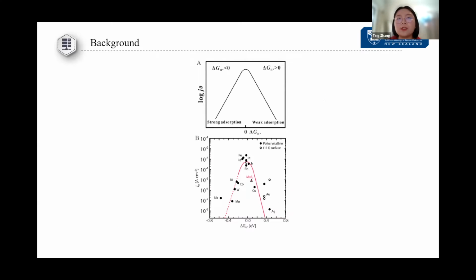According to the HER research, the interaction between the catalyst and the reactive intermediate should be appropriate. If the interaction is too weak, too few intermediates bind to the surface of the catalyst, and that will slow down the reaction. If the interaction is too strong, the reaction product fails to dissociate. The hydrogen cannot desorb from the catalyst, which also ceases the reaction by blocking the active sites. So the ideal value should be 0, which gives the highest HER performance.